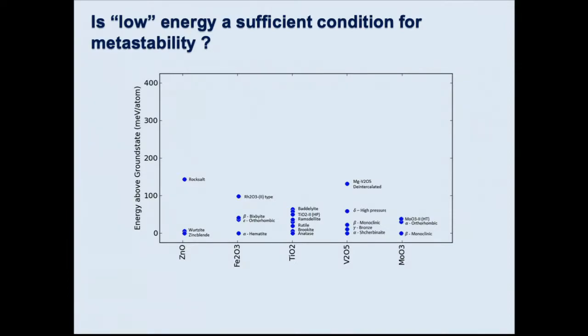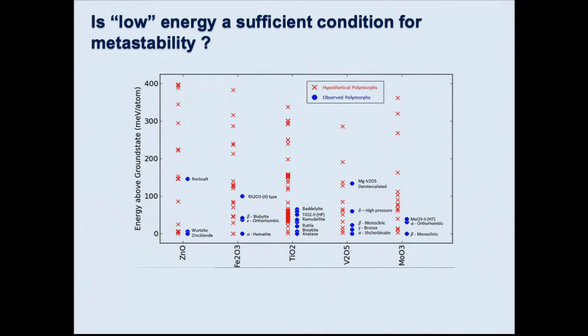Okay, then we did this test. You should always quit while you're ahead. So we did this test. We took some very well-studied systems, titanium oxide, iron oxide, vanadium oxide, and this is the energy of the known polymorphs. Like for titanium oxide, you have rutile, brookite, anatase, ramsdellite, et cetera. Then we, in the computer, made up a bunch of other crystal structures. Really, we would take known crystal structure types, but put them in that chemistry, and we calculate their energy. Damn. What it turns out to be is that there's a ton of possible crystal structures in this range of what we thought was metastability, 100 millielectron volt per atom.